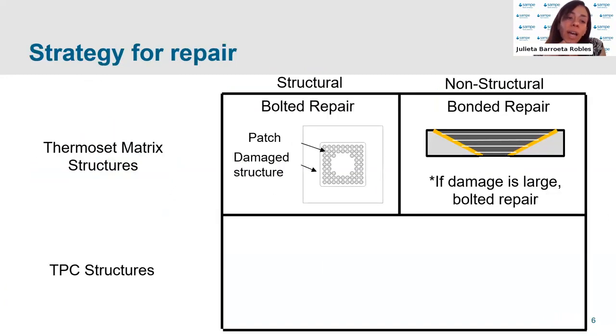So if we look at composite materials with thermoset matrices, if the damage is on a structural component, typically bolted repairs are applied, which involves using mechanical fasteners to bolt the patch onto the damaged structure. If the damage, on the other hand, is on a non-structural component, so if it's cosmetic, typically bonded repairs are applied, which involves preparing the surface, conducting a scarf, and using adhesive bonding to join this patch.